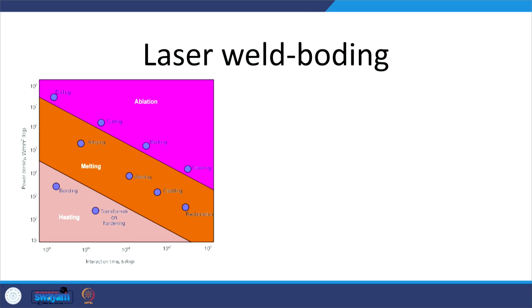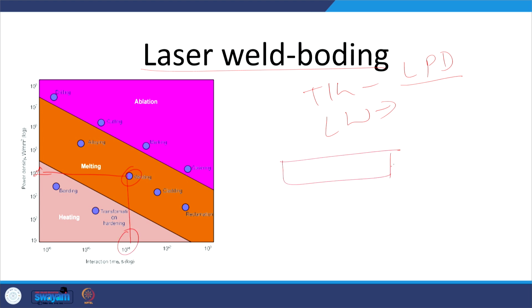Okay. In laser weld bonding, since TIG uses relatively low power density, but the power density associated with the laser is very high, especially for the welding purpose, say 10 to the power 4, and this is the interaction time. So, since the laser delivers a lot of heat in very short time, if an adhesive joint is there and we supply the laser forming the metallurgical bond, then the heat dissipation to the underlying base metal will be very less.